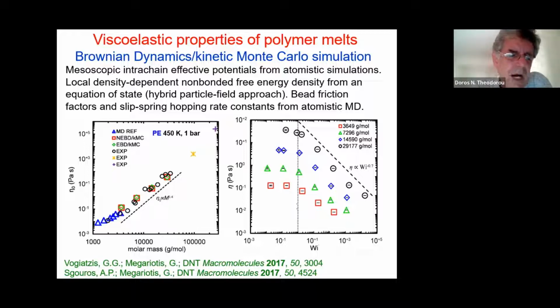And the two sets are exactly the same, which sort of points out to an internal consistency of this approach. And we see that we can indeed predict viscosities for these long chain melts, and the dependence on the molecular weight is pretty much what is seen also experimentally with these black points and the yellow star here, namely that the zero shear viscosity for long chain melts goes like molecular weight to the 3.4 power. This is a signature of entangled dynamics.